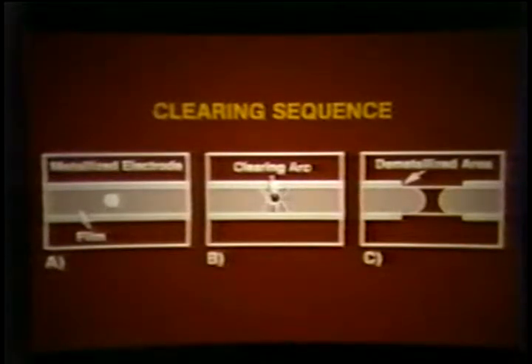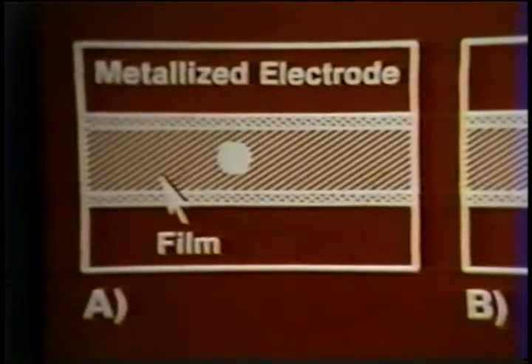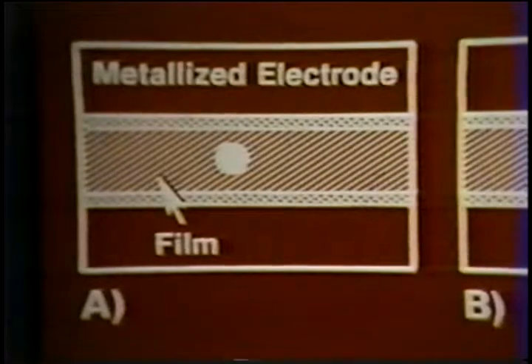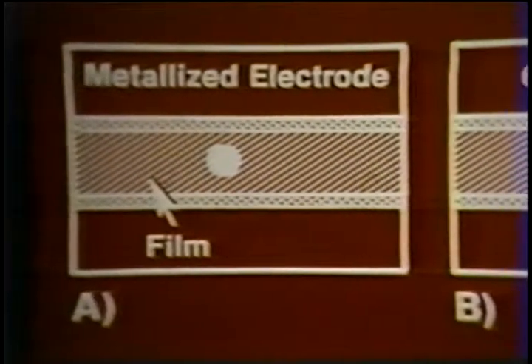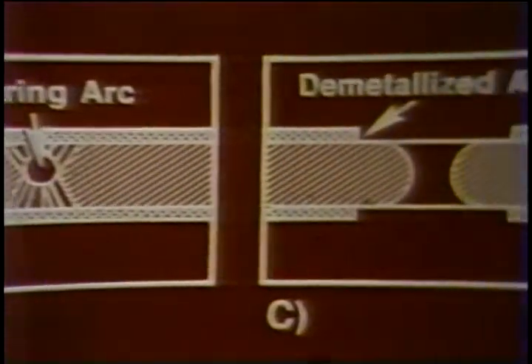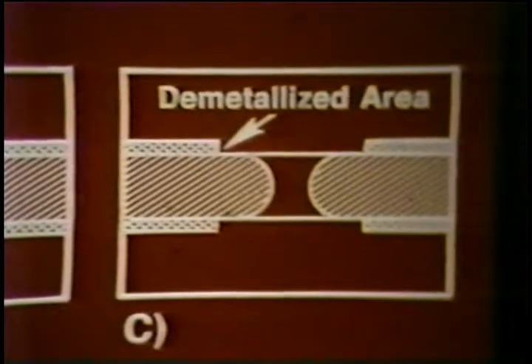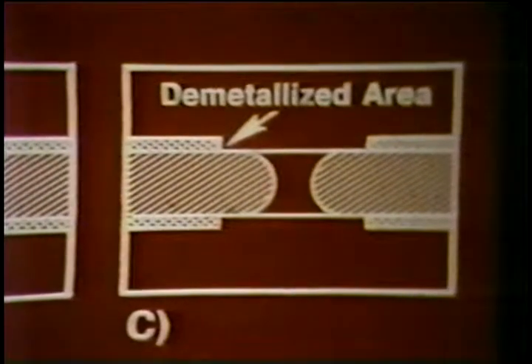On the left we see a dielectric with a defect present. This defect may be a dirt particle, a hole, or a scratch, or any other defect in the dielectric. During operation, this defect can cause a momentary breakdown. An arc can exist between the two electrodes, as shown in the middle. During this arcing, temperatures in excess of 2,000 degrees centigrade can exist in the dielectric, which vaporizes the dielectric and the aluminum electrode from around this defect site, isolating it from the rest of the electrode area. This takes place in approximately 10 microseconds and involves an almost imperceptible reduction in the capacitor voltage and charge stored